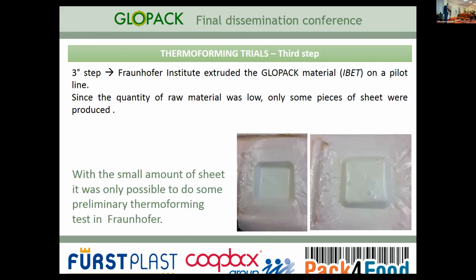As a third step, there was the thermoforming of material produced by IBET and extruded by Fraunhofer. In this case, the thermoforming tests were not made in Coopbox, because the quantity of the material was not so high, and in the extrusion tests that were made in Fraunhofer, it was not possible to find the right extrusion parameters. So only a small quantity was extruded, and it was decided to do some very preliminary thermoforming tests directly in Fraunhofer. The results are not so bad, because the flexibility was quite a bit better than the commercial PHBV. The only thing is that the quantity was too low to have a clear result.